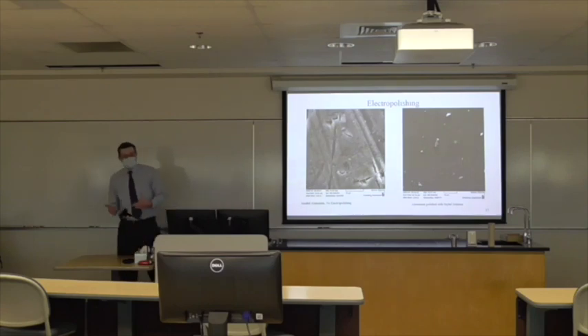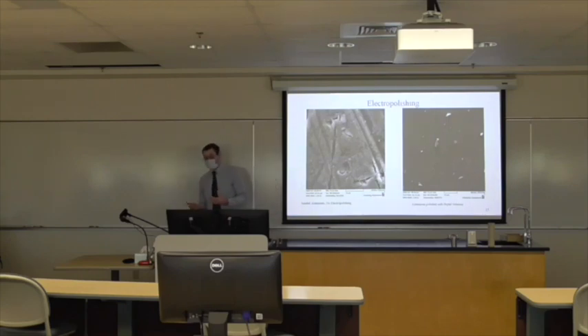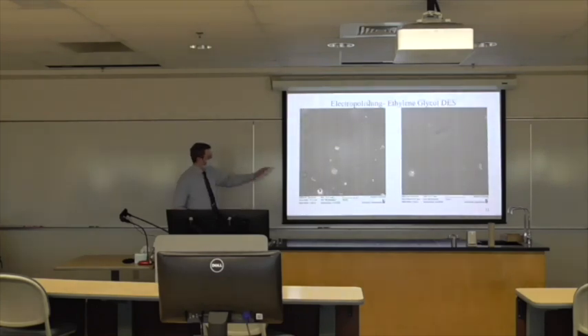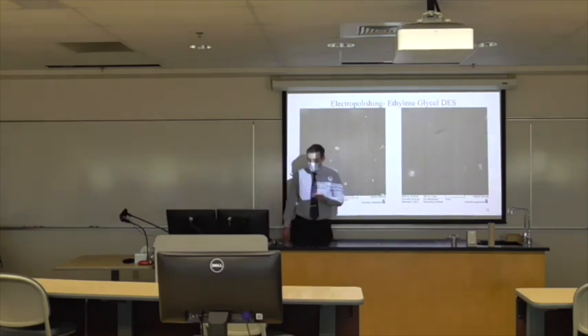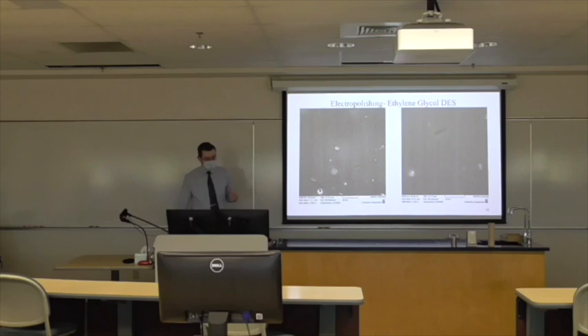Now, one DES that works, and that there is published information about it working for electropolishing, is a choline chloride ethylene glycol DES in a 1:2 ratio. So that works pretty well. It produces a situation like this, where at 7 volts, you're able to electropolish aluminum to make it reasonably defect-free. Now, this 99.5% aluminum here works well enough when it's polished with ethylene glycol DES. This is done at room temperature, so we're getting better.